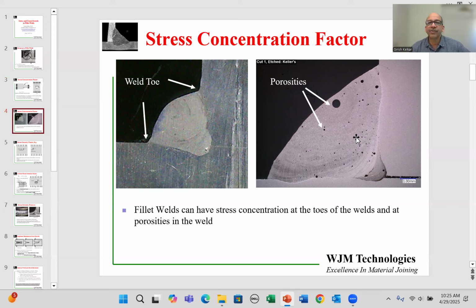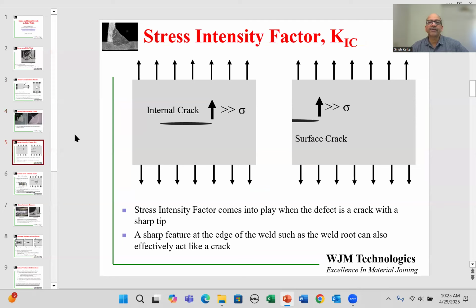On the right, I'm showing you a cross section of a weld with porosity inside. And here again, there'll be a stress concentration effect when the stress lines flow through the weld from one component to the other component. Another important factor that you need to realize is what is called a stress intensity factor.